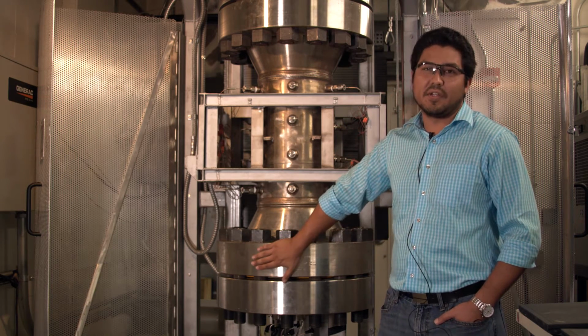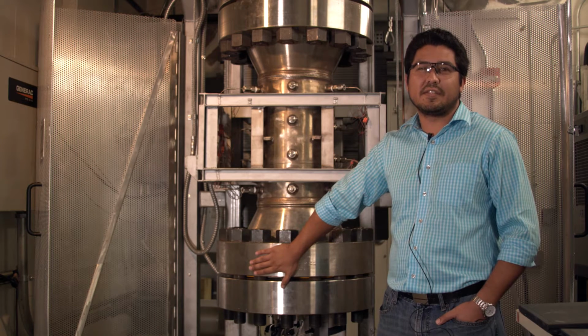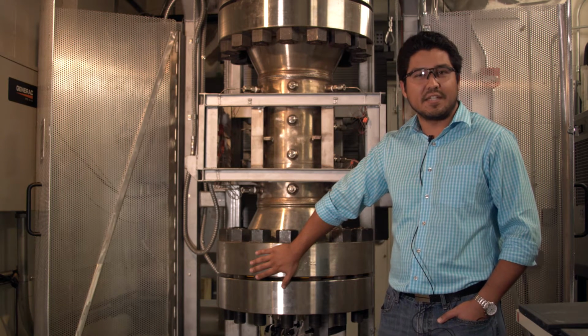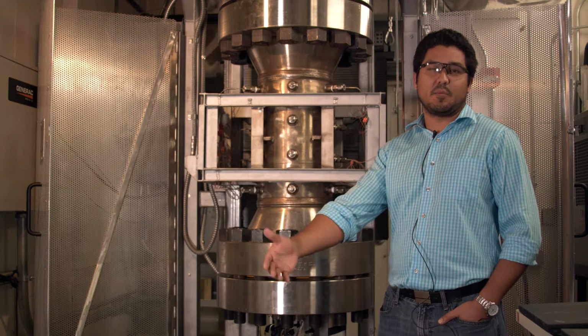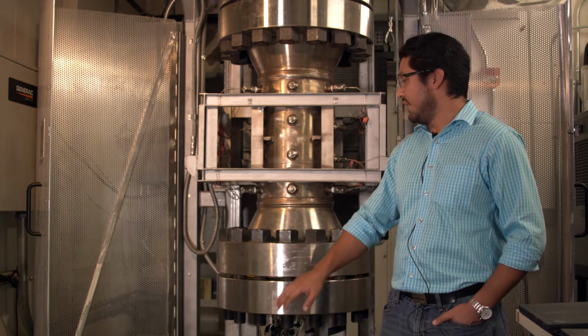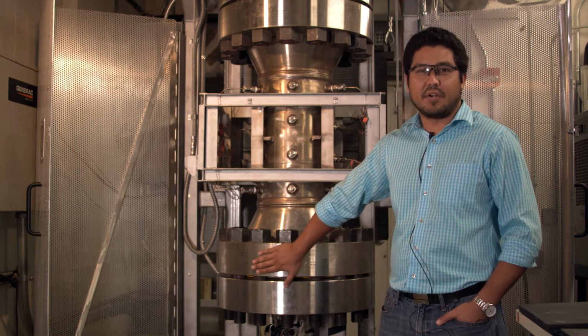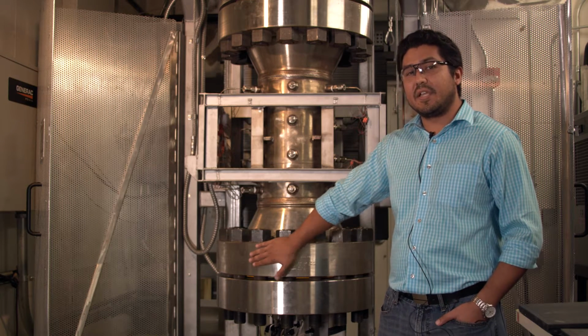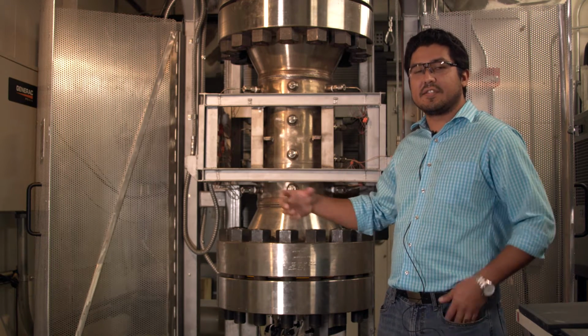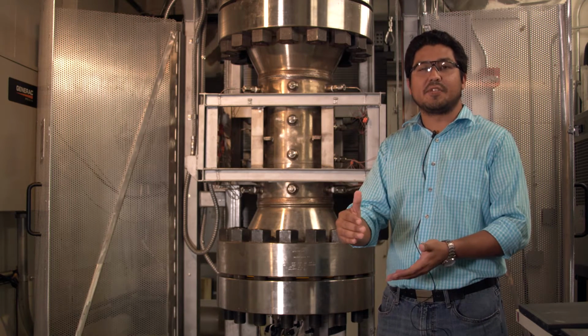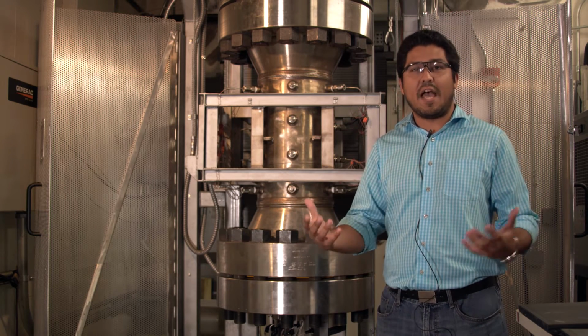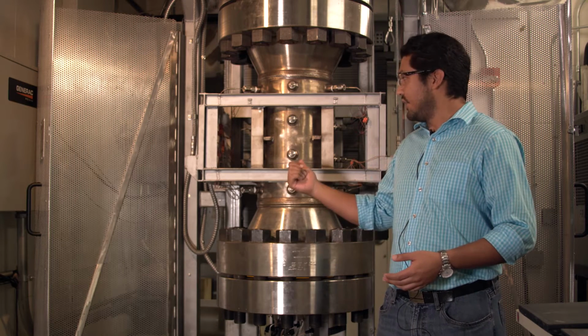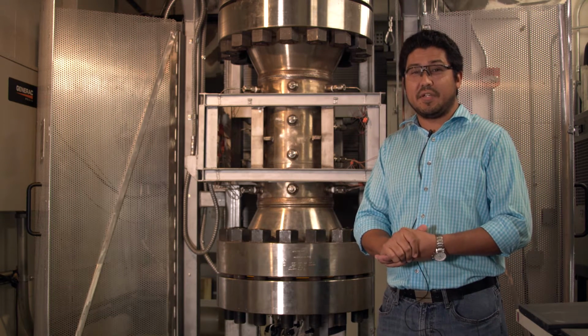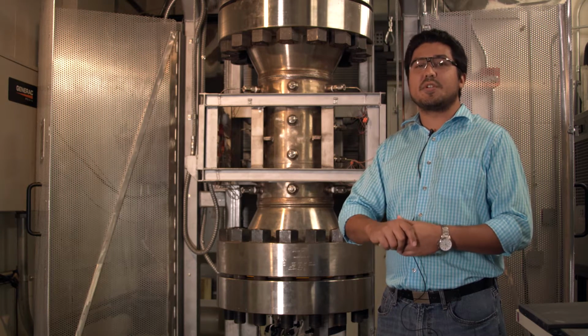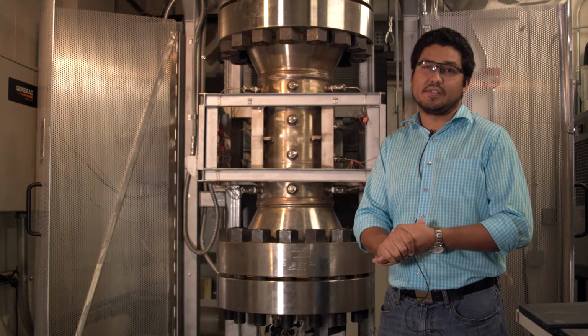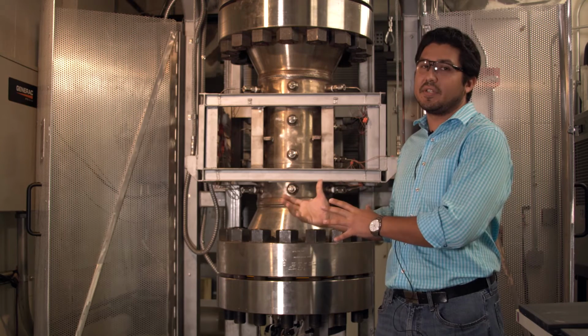Now this is a very special furnace. There's only about 2 of these type furnaces in the world for processing high temperature superconductors. One of them is a private company. It's a massive system. This is a very research development furnace. And what we can do with this is we can increase the pressure of the inside hot space to about 50 atmospheres. We typically live in about a 1 atmosphere environment, Earth. So we increase the pressure up to about 50 atmospheres, and we drive the temperatures up to about 900 degrees Celsius. So very, very specialized furnace.